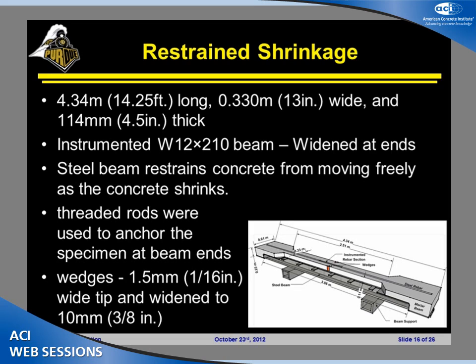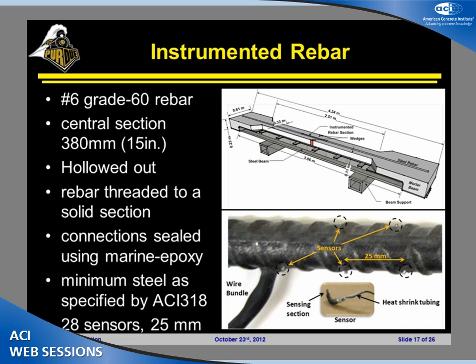And one of the things we're really looking at is not only the width of the crack that forms, but we think that one of the most important things, in addition to the width, is how much debonding we get along the length of the bar. Because if we get debonding along the length of the bar, chloride ions can move very quickly along the length of the bar and start to corrode a substantial length of that bar.